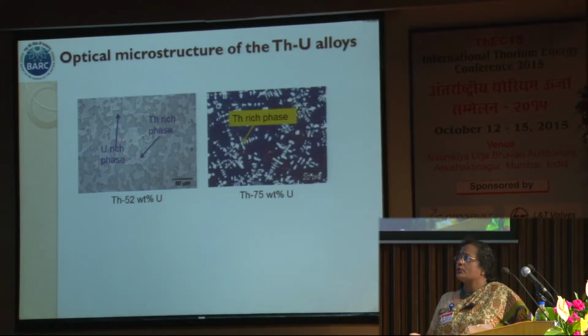And here you are really not able to come out of the problems of uranium metal, meaning anisotropy or low melting point, those effects will be there. So there is no point in going into this matrix. Here you can see it is thorium 75 weight percent uranium. Here the matrix is wholly uranium and thorium is in a dendritic distribution. So this also gives you the maximum problem of uranium metal, whatever we face.